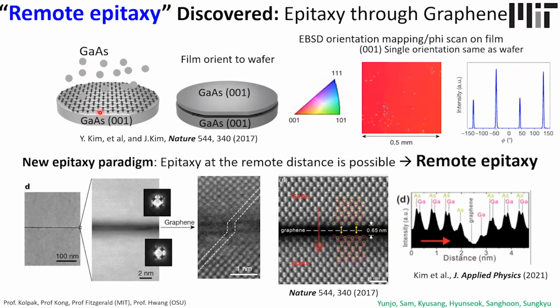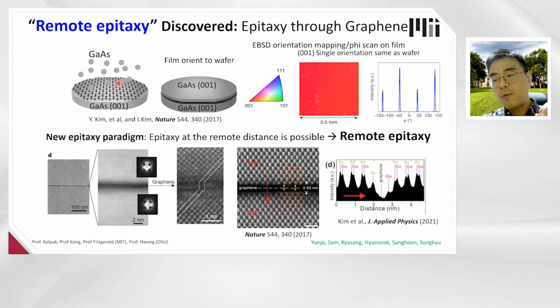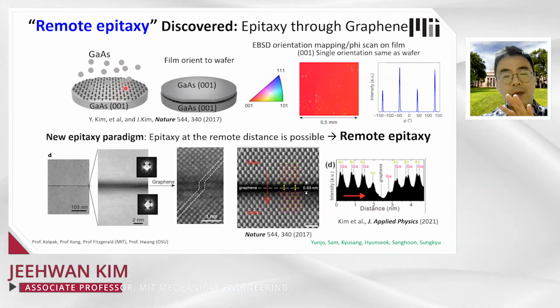But anyway, we discovered that even if there's graphene on top of the wafer, if you perform the epitaxy of the same material, then this material still can follow the crystalline lattice of the underlying substrate, even if there is a monolayer graphene. The reason is quite simple. Of course, I can say that because we completely understand why by now. If there's graphene in the vertical direction, there will be a very, very weak van der Waals field applied. But at the same time, on the surface of the semiconductor wafer, there will be quite strong ionic bonding interaction applied in the Z direction, because this ionic bonding force is supposed to be much stronger than the van der Waals force from the carbon in the graphene.